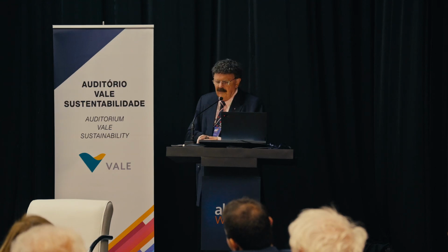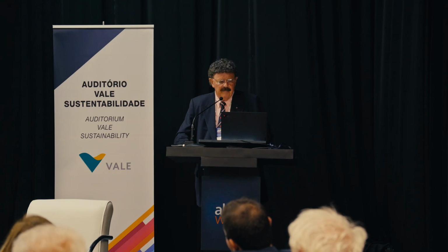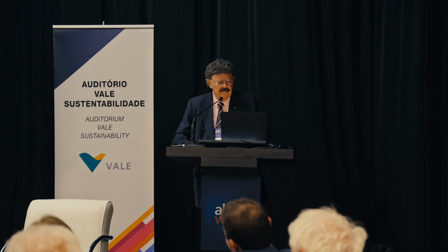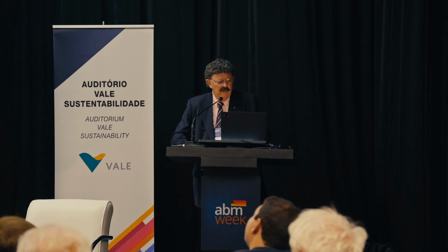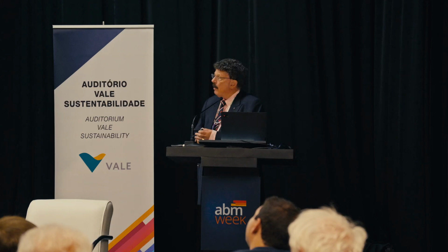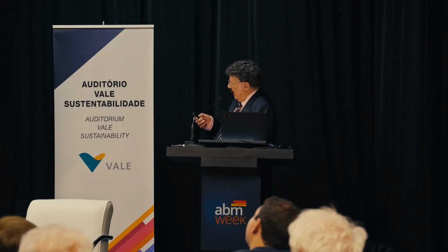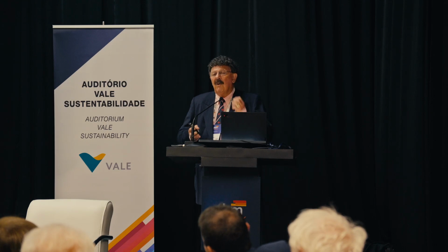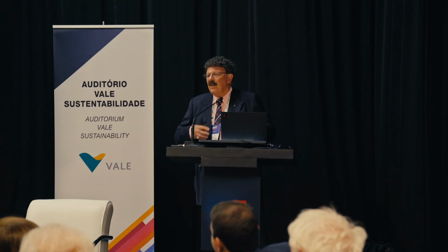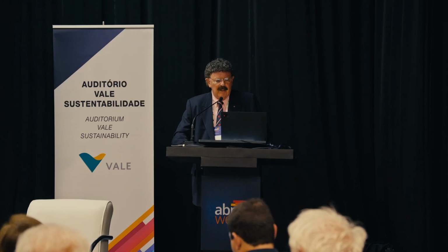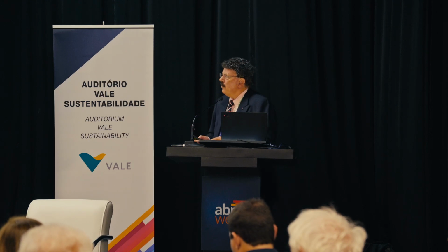And these stacking faults are extremely, let me go back again. They're extremely good at blocking dislocations. You can see a dislocation pile up here coming against the stacking fault, and it's very, very effective. So this seems to accentuate everything we've seen before. High strength, high ductility because of the motion of dislocations. But if we look at the properties, they're very interesting.